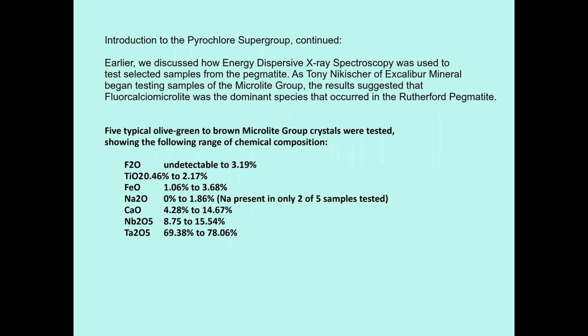Now, I'd like to share some additional information about microlite. In 1935, Jewel J. Glass reported that the olive brown variety of microlite was usually embedded in chatoyant albite variety peristerite, otherwise known as moonstone, while the amber and reddish yellow varieties, many of which were transparent, occurred in the interstices of clevelandite. Glass was also the first to report that X-ray analysis of both varieties had shown a high degree of absorption, indicating that because of the disruption of the crystal structure by radiation from contained or nearby radioactive atoms, the crystal structure had become amorphous or metamict.